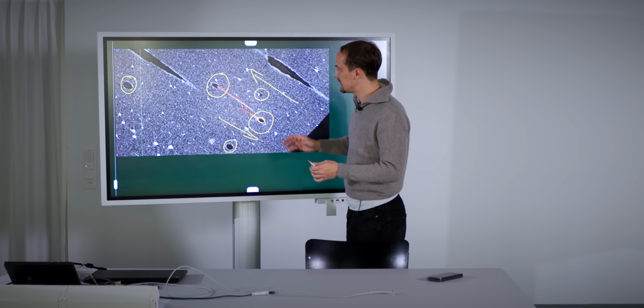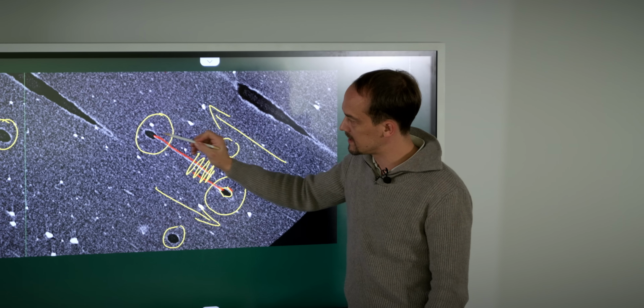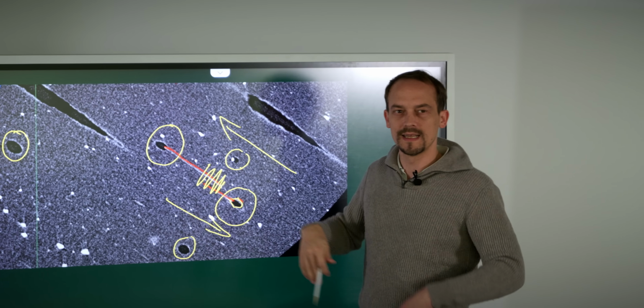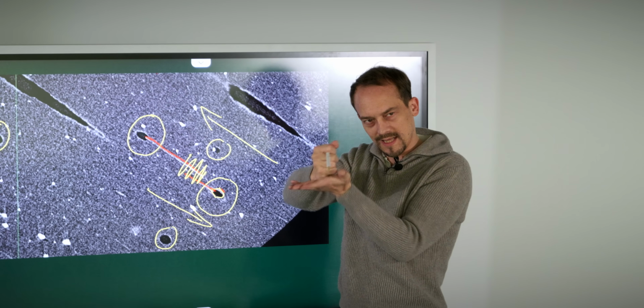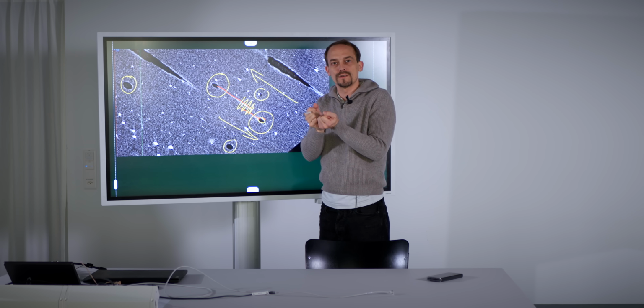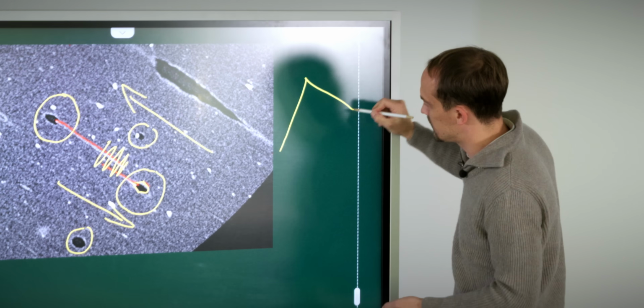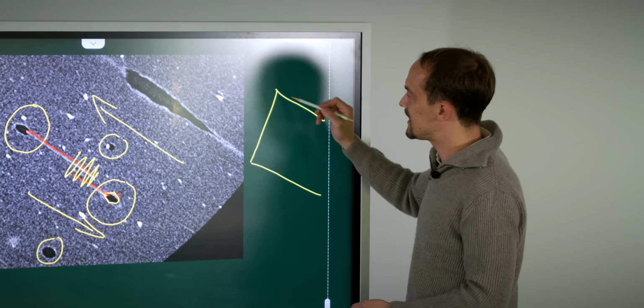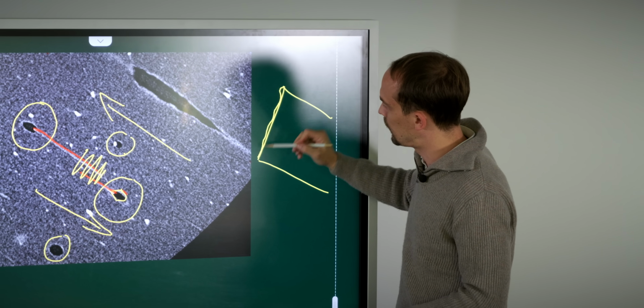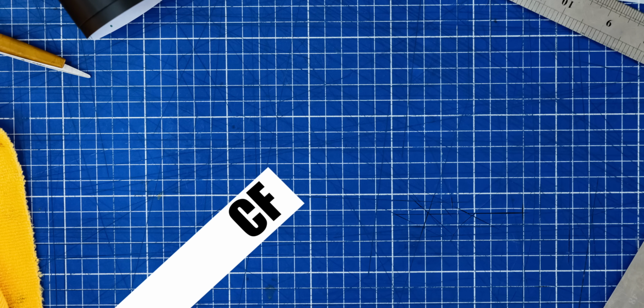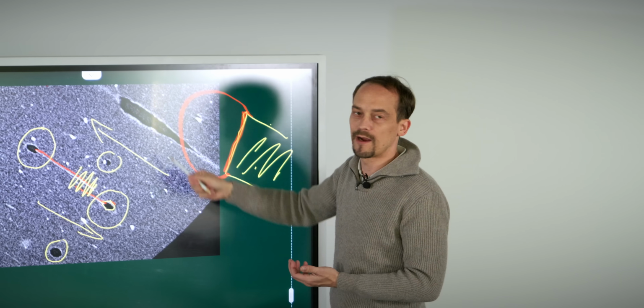One of my theories is that the carbon fiber actually gets laid down, and because the material always hardens already back here while it's still extruding, the material around it is still kind of moving because it's squished by the nozzle extruding, but the carbon fiber itself is already stuck. The ends of carbon fibers are basically sharp corners. The material detaches from there because of that corner, because of the stress concentration, and it drags out a drop where there is simply negative pressure, or air is pulled in. An air bubble is created.